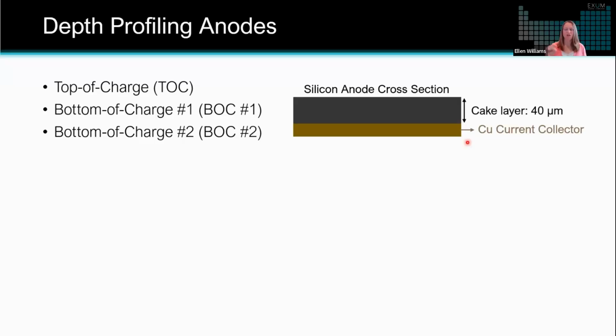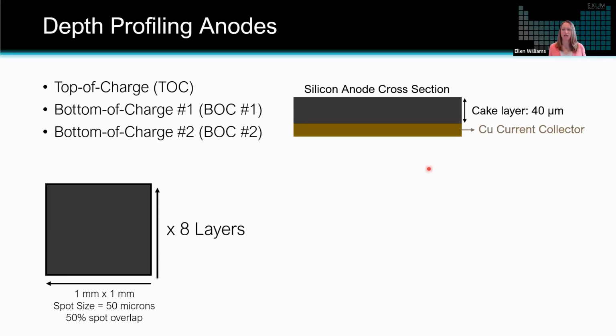We've got this 40 micron thick silicon anode that was deposited on a copper current collector. And the way that we analyzed these samples is with a 1 millimeter by 1 millimeter area. We used a 50 micron laser spot size, and we chose to overlap that spot as well. So we've talked about the versatility on the mapping side of things, of being able to adjust the laser spot size to change the resolution of your map. On the depth profiling side of things, the user can change the laser power so that you're removing more or less material based on the power that is going into the ablation process.